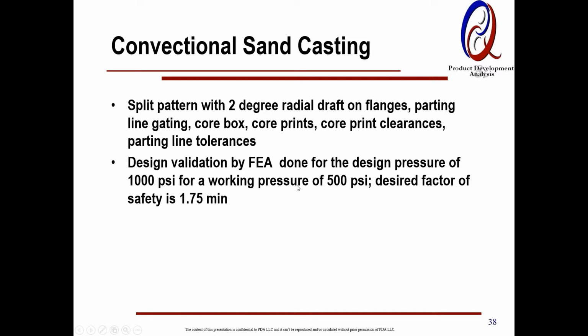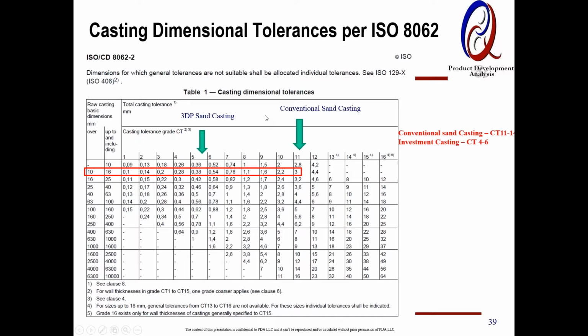Conventionally it's a split pattern with 2-degree radial draft on flanges, parting line gating, core box, core prints. Core print clearance is 1/16 of an inch per side, and we converted that. We looked at that, and so the point here is, if this is one of the standards being used in the industry for dimensional tolerances, ISO 8062. The conventional sand castings are typically in the range 11 to 14.